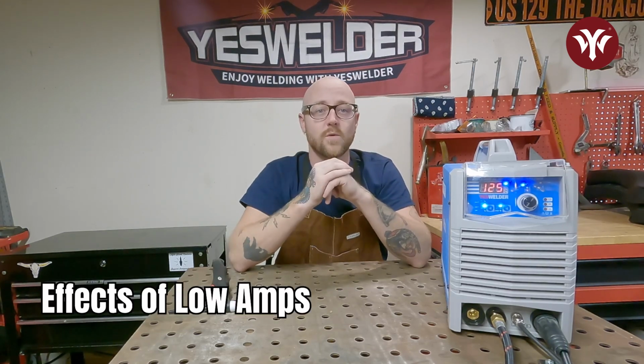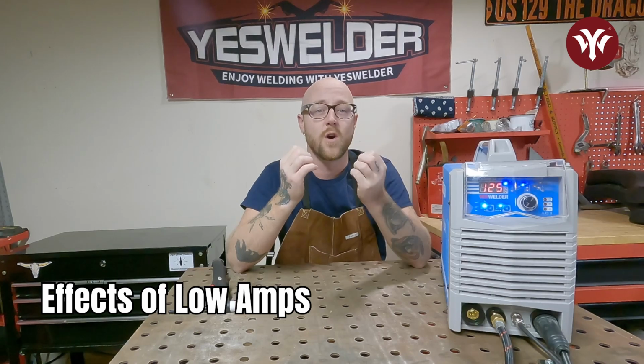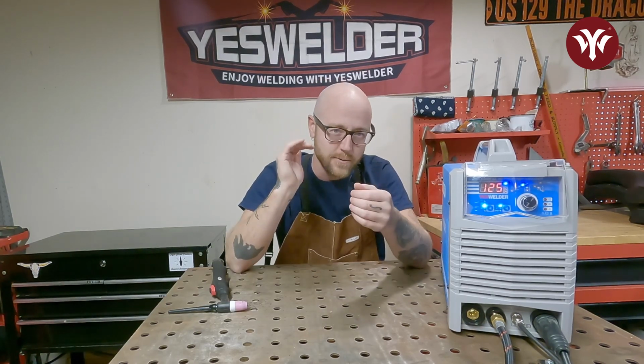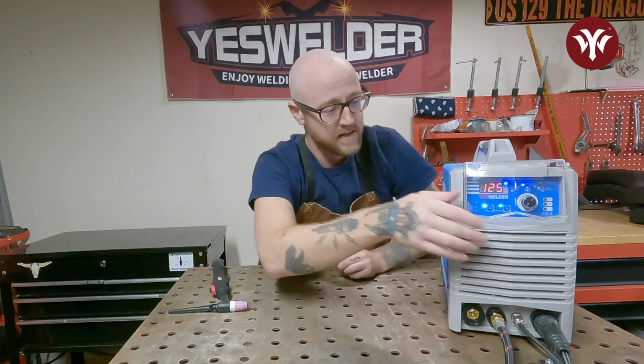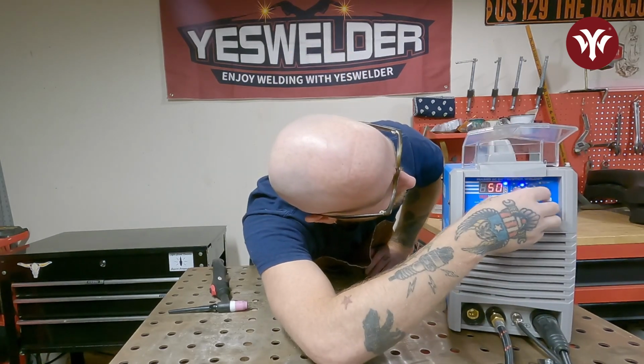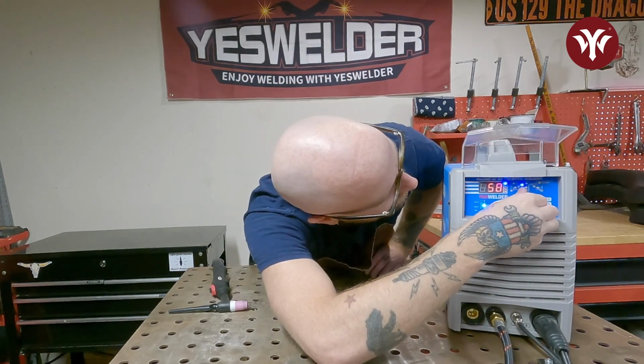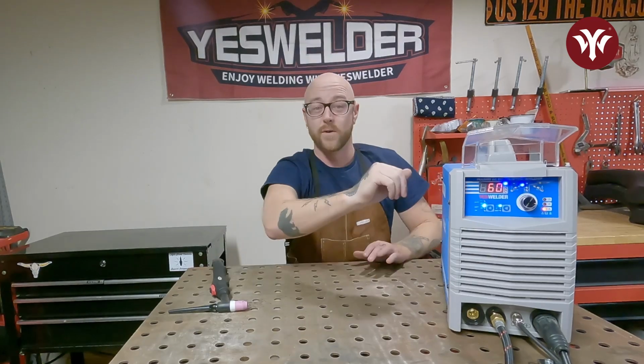But for the first weld, we're going to actually make it cold so you know what it looks like and what the puddle feels like when you're running too low on your amps. So I'm going to turn this way down to about 60, which is a little under half of what it should be. So let's run that weld and see what it looks like.